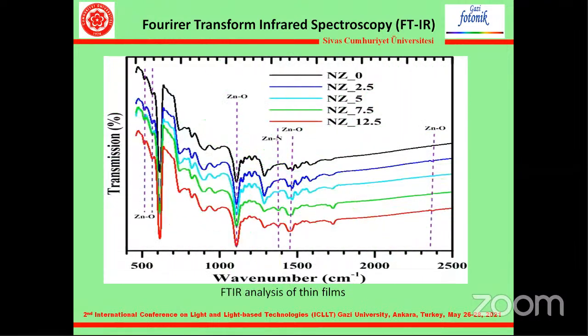Fourier transform infrared spectroscopy. Here we will see the bonds in the structure of molecules. Fourier transform infrared spectra of zinc oxide thin films produced with different nitrogen percentages are given in Figure 4. As can be seen from the spectra, all the materials produced seem to have a similar spectrum, but with nitrogen entering the film, a peak began to be absorbed at approximately